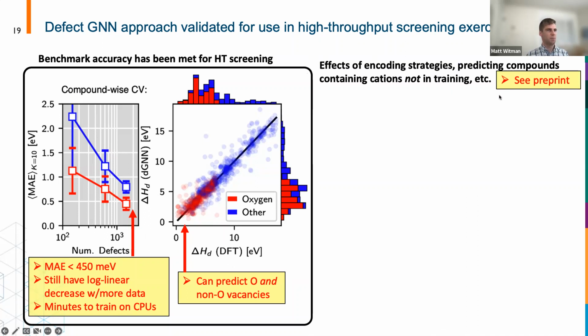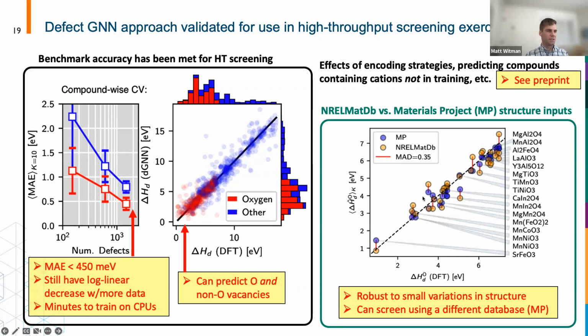So some things I won't talk about today, but you could take a look at in the preprint are the effects of different encoding strategies, and what happens if you try and predict a compound that has a cation that wasn't in the training set, and things like that. But just to convince ourselves that this model is high performing and not overfitting, we can apply the model to two different crystal representations, one from the Materials Project and one from NREL MatDB, which is where the training data was derived. And for all these structures that only have one symmetrically unique oxygen site, we can plot the difference between those two predictions, and that difference is below the mean absolute error. So the model is robust to any kind of small variations in crystal structure or DFT settings.